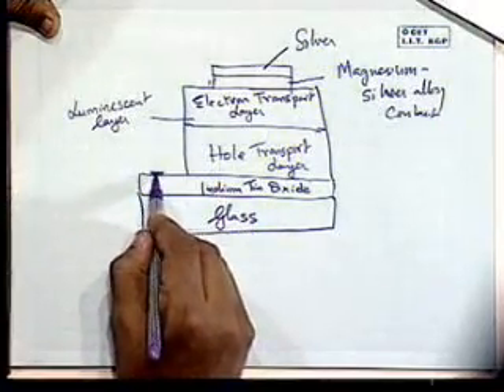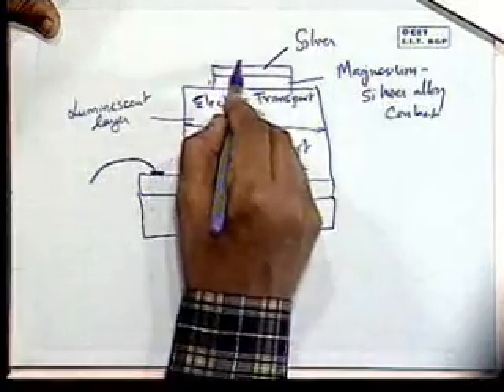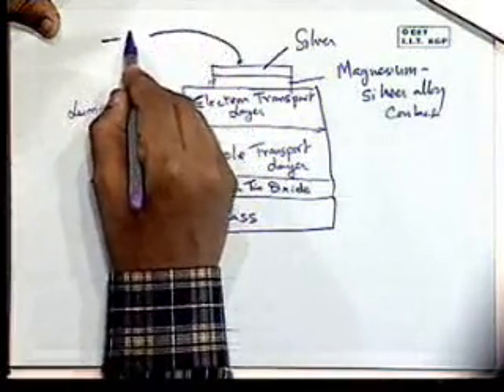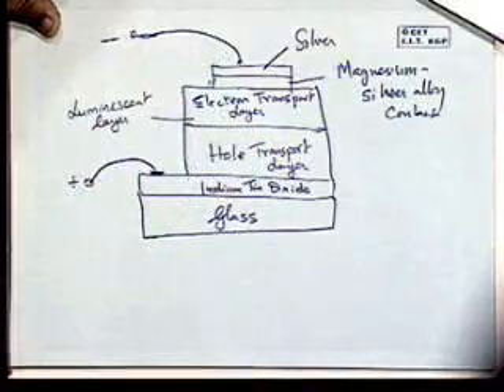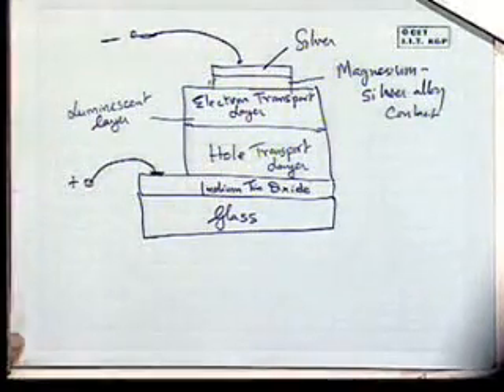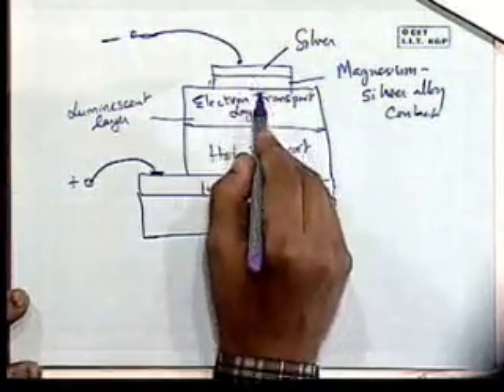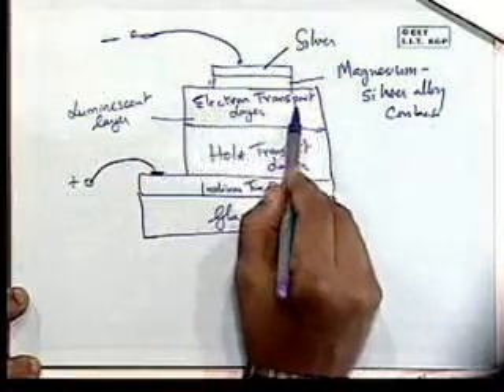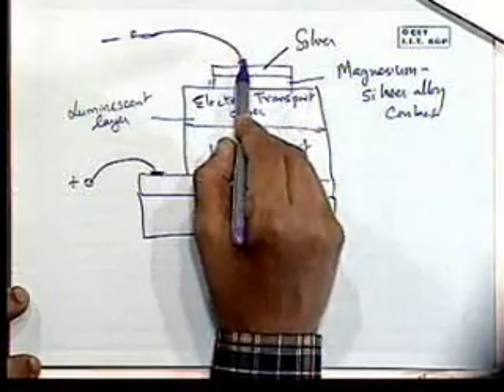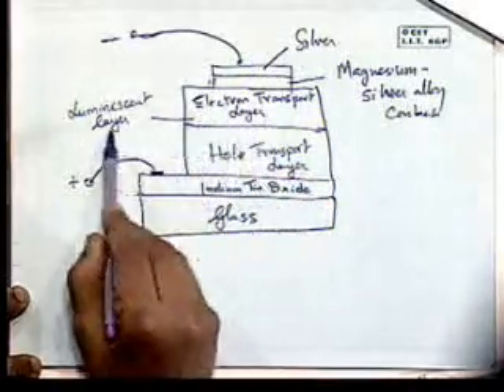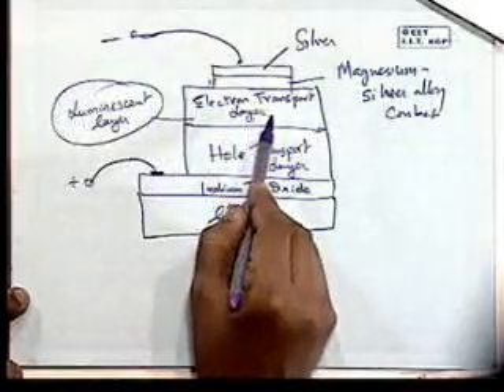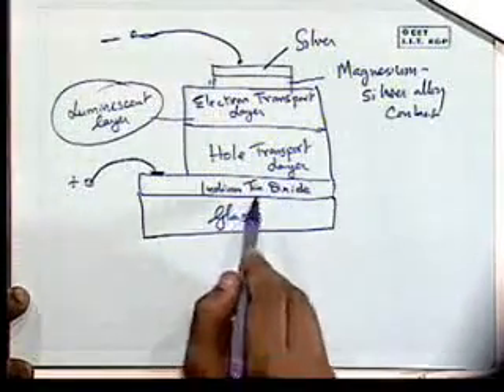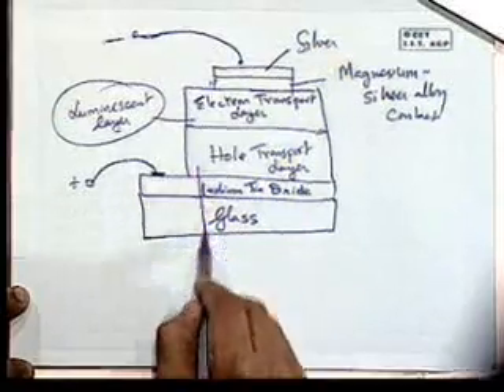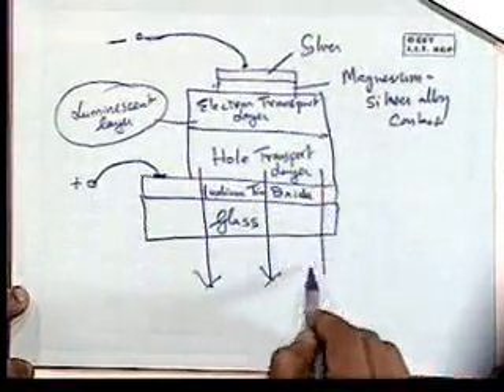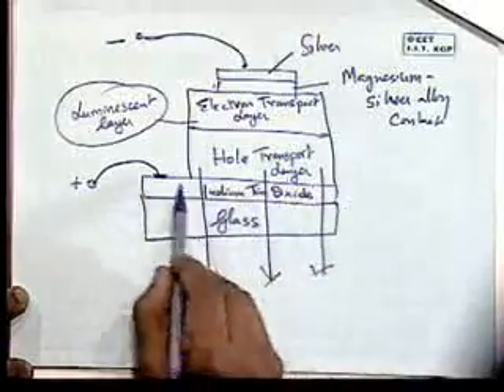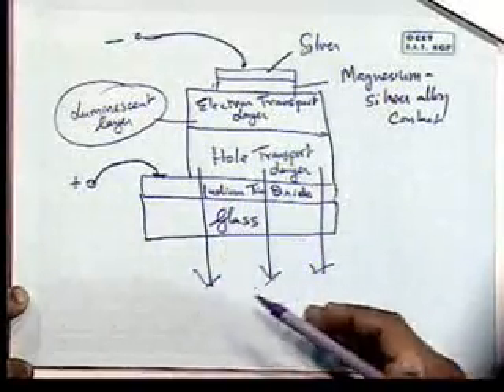To the indium tin oxide contact, you make one wire. To the top here, you make another wire. Attach the sources, and there we go, we've got an LED. The hole transport layer injects holes into this luminescent layer. The electron transport layer allows the injection of electrons from the other side, and they combine in the luminescent layer, which in this case is the same as the electron transport layer, though you can have it differently. And light is produced, which is emitted in this direction through the transparent contact. ITO is transparent, and so is glass. So below here we will get light.